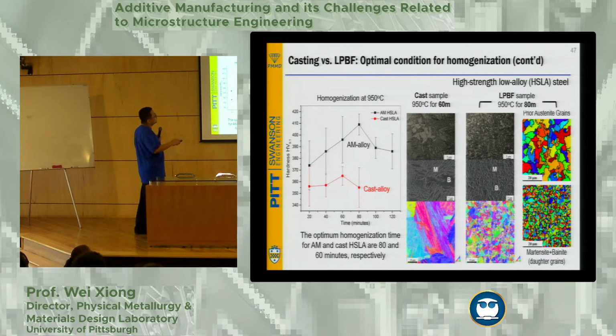So if you look at this, this is a casting example of the HSLA, and this is the LPBF sample. As you can see, these grain structures, after reconstructing with the prior austenite, are actually quite different from the cast example.